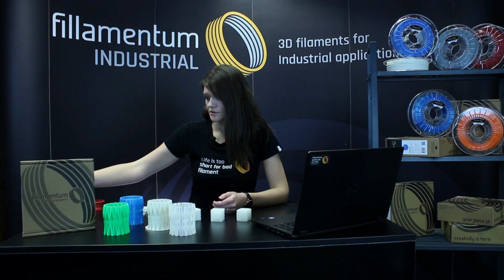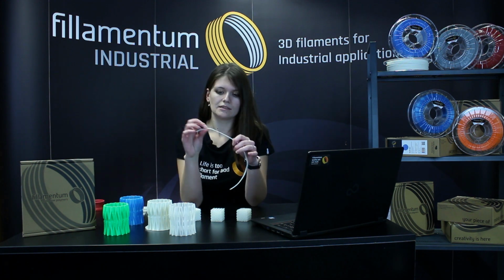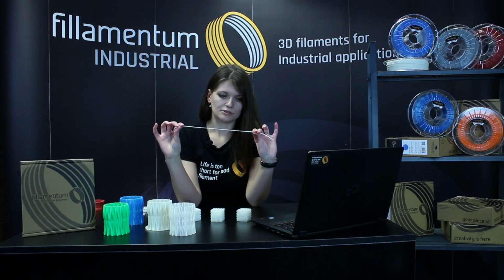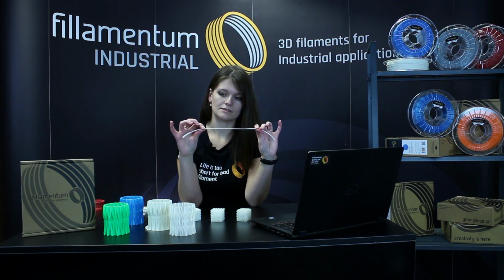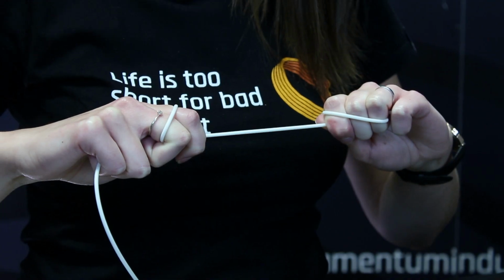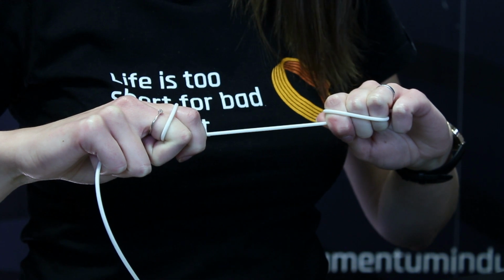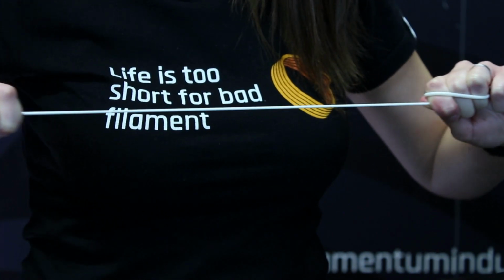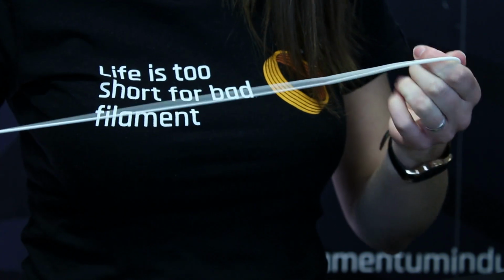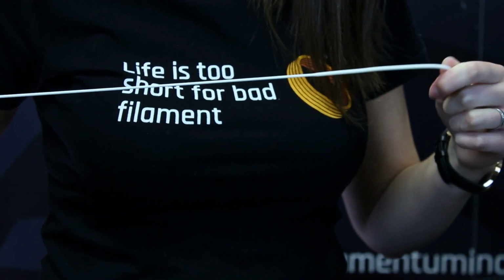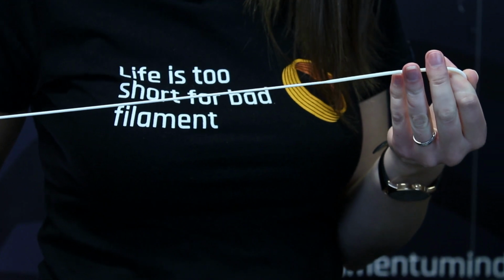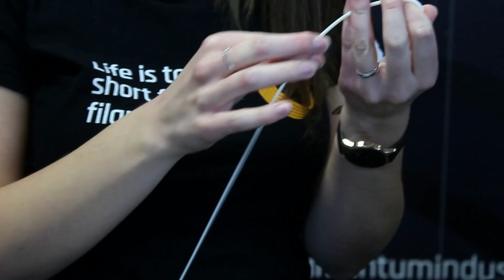We also connect this chemical structure with the creating of a neck. It is also in case of TPE that we apply the stress, and there is a thinner part of the filament. It's not in the case of TPU, it has very high reversible deformation. So this is how they differ. It's better to avoid higher elongation of TPE material. It is better to use TPU.